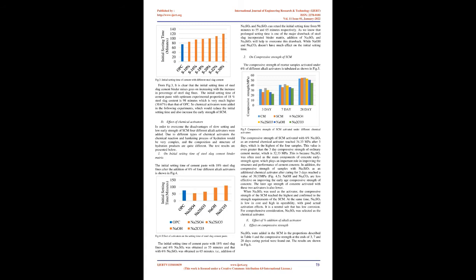The lower early age strength can be attributed to the slower reactivity of slag due to presence of unhydrated large particles as per the available literature. This is due to the fact that the reaction of CaO present in steel slag fines is very fast and highly exothermic. The hydration products generated due to rapid reaction of CaO had weaker and fluffy morphological crystal structure with more cracks and defects, which weakened the early strength.